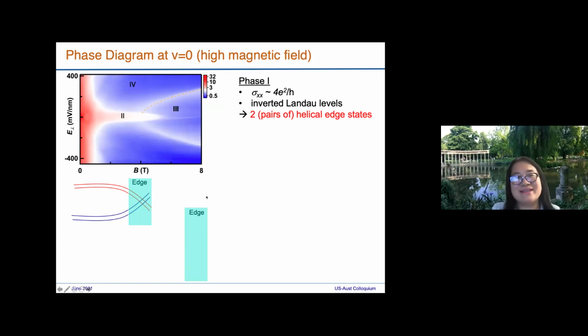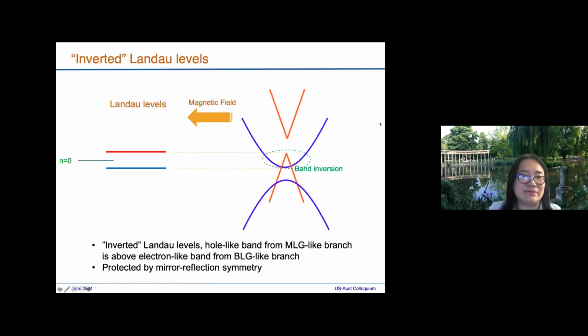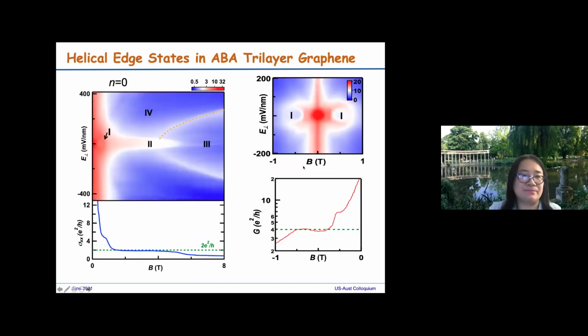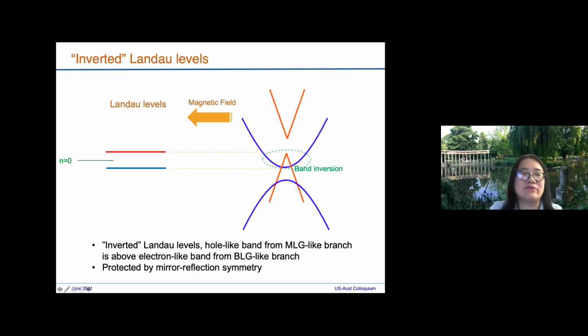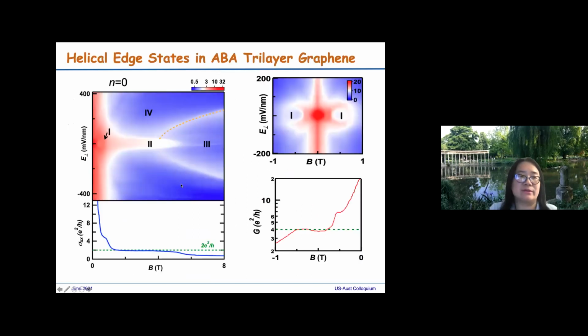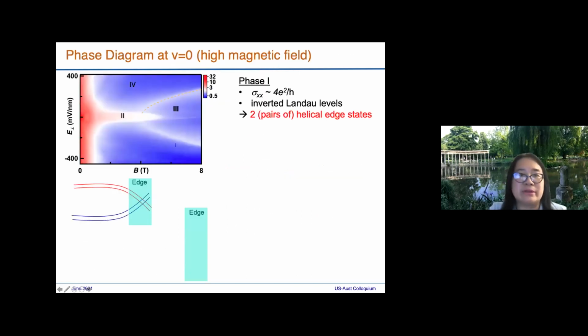All right, so phase one turns out it comes from, again, this quantized conductance of 4 e squared over h. It has 2 pairs of helical edge states. It comes from these inverted Landau levels. So remember, we have this pair of inverted Landau levels: the red one, which is the hole-like one, above the blue one, which is the electron-like one. But also remember that they come from different bands with different parity under the mirror reflection operation, so they do not mix.